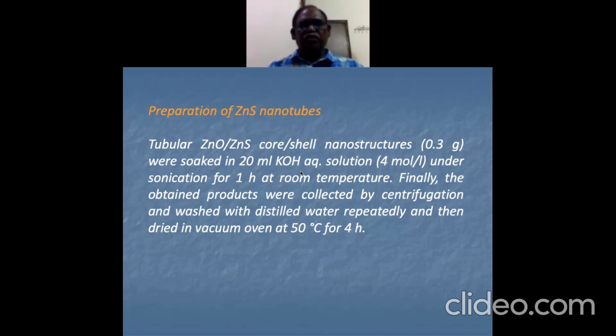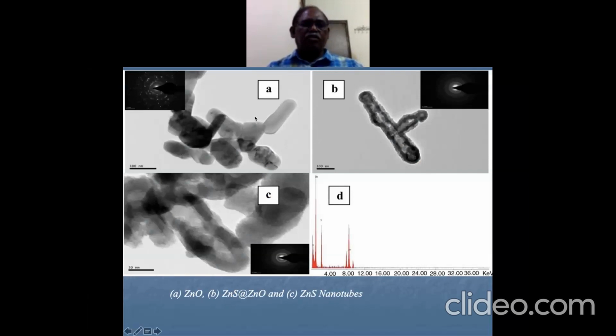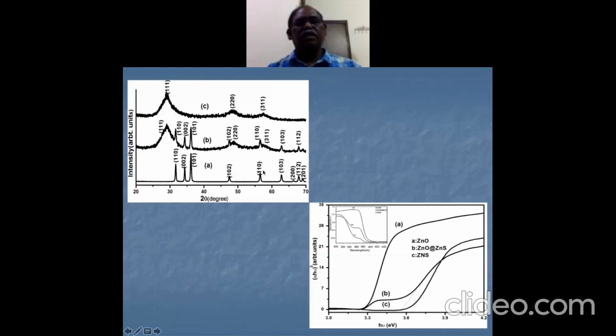So you can see over here, this is for ZnS, and this is for the composite system, and these are the nanotubes over here. So by tailoring a little bit the same kind of system, you can make different kinds of structures. And the XRD also shows the same thing. So this is the ZnO, and then this is a composite system, the core shell kind of thing. And then when you soak it, you get the ZnS nanotubes. And the band gap also changes. This also shows that there is some change.